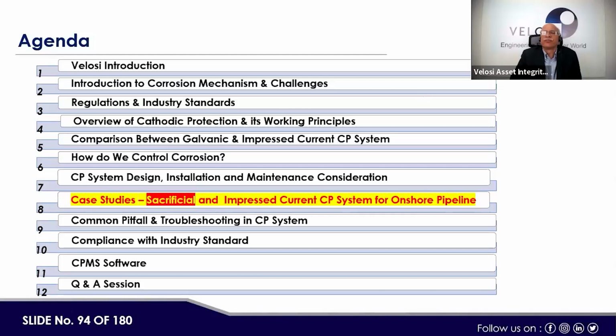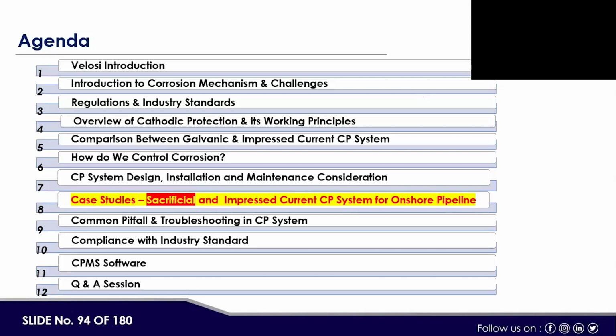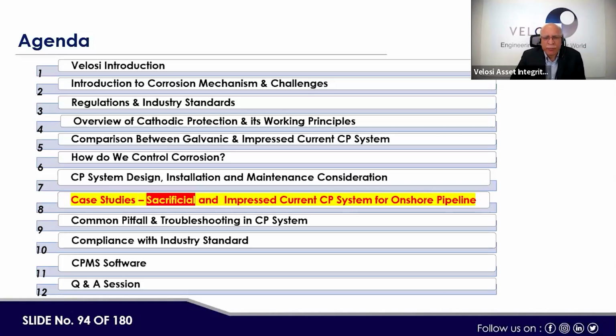Yes. So my question is how frequently we can monitor the CP system, specifically for underground piping. Normally, you have test posts along the route of the pipeline, and then there are TR points. Various companies have various frequencies. It varies for the test points from 1 month to 6 months, and the TR testing is normally on a yearly basis, but it can be established based on your own experience and company strategy. If you have developed your inspection and maintenance program for the CP assets, then it can be fixed based on the mean time between failures. If you have seen problems with your CP system, then your frequency has to be increased. Otherwise, it can be extended for a longer period.